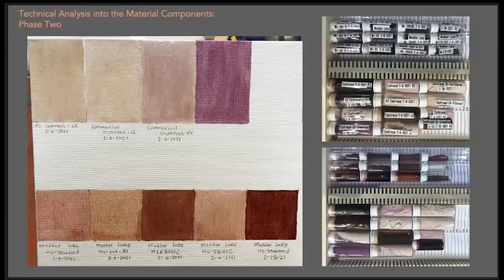Once the various shades of cochineal and madder dried, the pigments were ground first in a mortar and pestle, then mulled on a glass slab with linseed oil in order to create a transparent glaze similar to those used by the Limners. We next plan to combine the glazes with a white pigment, to recreate the flesh tones, and a heavier bodied red to recreate that apocalyptic sky.